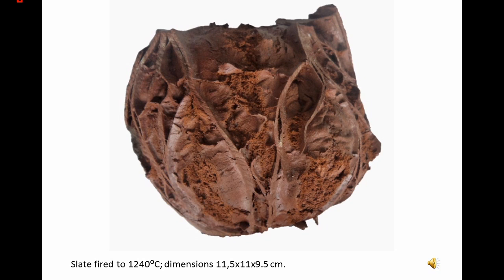The initial compact volume becomes expanded and opens up its interior, but black slate recovers the hardness and mechanical resistance. The relationship between volume and weight does not substantially change in the temperature range of 1150 C to 1240 C, but if different black slate pieces are in contact, due to vitrification, they become more firmly fixed to each other. The expansion amplitude of the black slate is primarily correlated with the specificities of the initial black slate, the firing cycle, as well as with the dimension of the tested piece. That is, factors such as mass and weight have influence in the expansion amplitude.